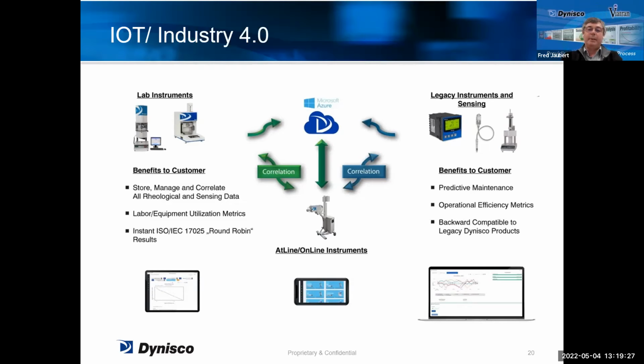We have also now started to build what we call Industry 4.0. Basically, we can collect the results of legacy instruments, old melt flow indexers, old capillary rheometers, and also new lab instruments, and link them through a cloud to the measurements that we can do online. So, for example, we can run our Dynisco Indicator online and run a capillary rheometer test every 8 hours, and then check that the measurement given online is really confirmed by the measurement in the lab, for better and more accurate production follow-up.